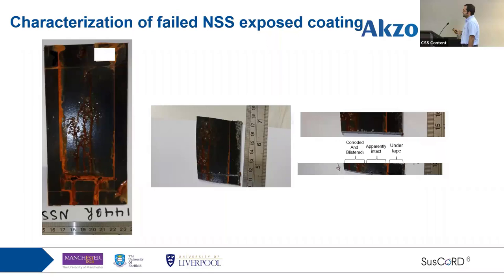So having said that, now I realize that actually in the panel that is failed, we have an area which is showing a lot of blisters, but then we have another area which is not showing corrosion formation. So I decided to look at these different regions, and I prepared a sample from this. We have an area which is under the tape, so it hasn't been exposed to the environment, then an area which doesn't show any failure or corrosion, and then an area which is full of blisters and corrosion products.